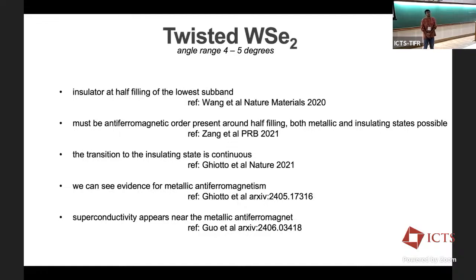Yeah, so I have a question related to the first question. You see there is a change in the slope of the Hall, and you attribute it to its being multiband. But does that really tell that antiferromagnetism is there from the Hall data? No, all it tells you is that, if you take the data literally, it's multiband, that there is a Fermi surface reconstruction. If you ask yourself what is the real evidence that it's a spin density wave versus a charge density wave, for example, it would just be the sign of the interaction, which we have no reason to believe is attractive. And so that's really a theoretical statement. But any Fermi surface reconstruction would reconstruct the Hall effect. Okay, thank you.